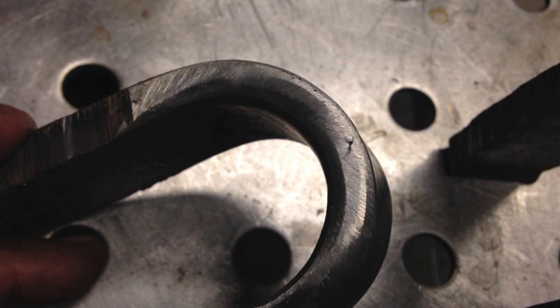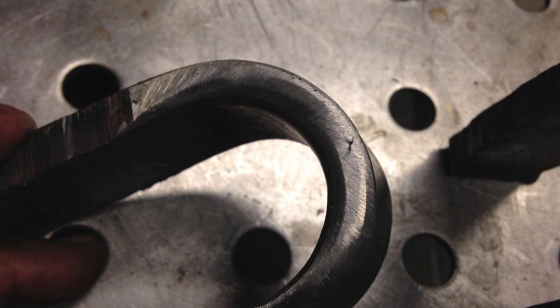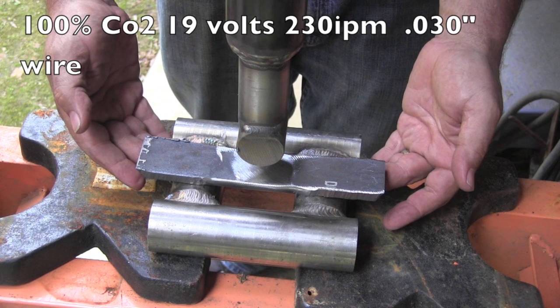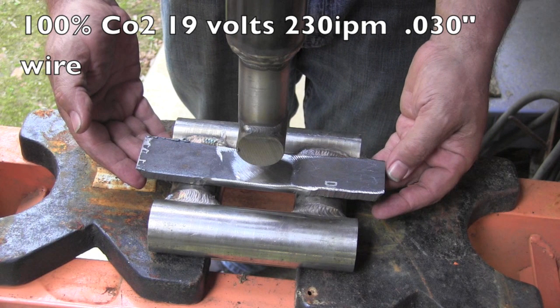But watch the very front leading edge of this pass. Looks a little iffy, doesn't it? It looked a little iffy to me going in, but I thought, well, maybe it's getting in. Maybe it's not. It's kind of cold. Definitely should be about 22 volts instead of 18.